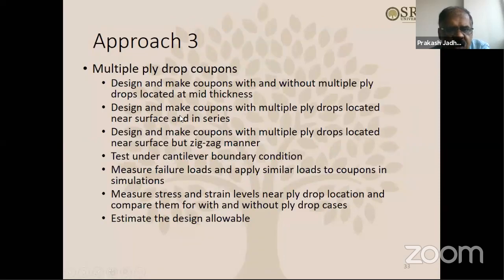So basically, design and make the coupons with and without ply drops located at mid thickness. Then design and make coupons with multiple ply drops located near the surface and in series. And the third one was, of course, located near the surface but in a zigzag manner. Again, we are using the cantilever boundary condition. Measure the failure loads and apply similar loads to the coupons. Measure stress and strain levels near the ply drop location and compare them for with and without ply drop cases. Then estimate the design allowable. So we'll show you what happens exactly.